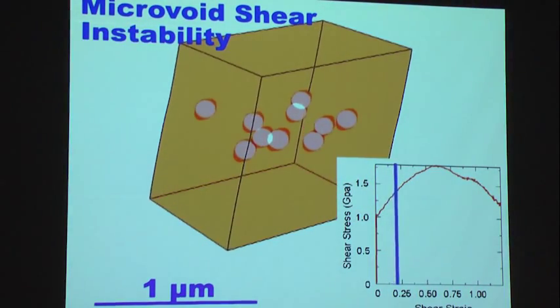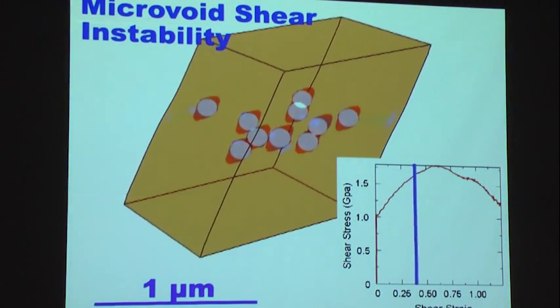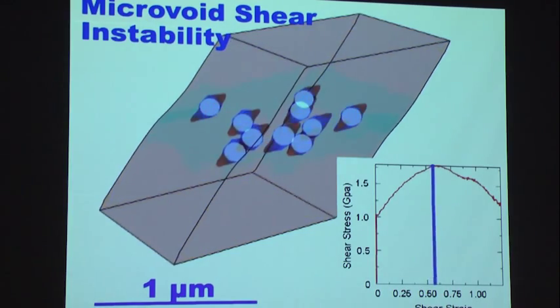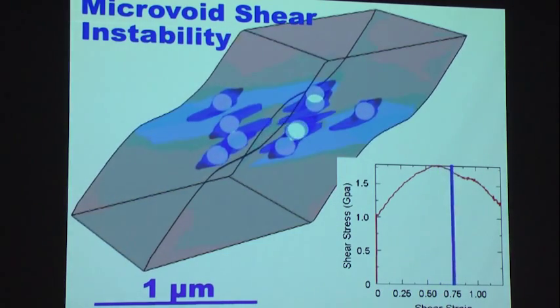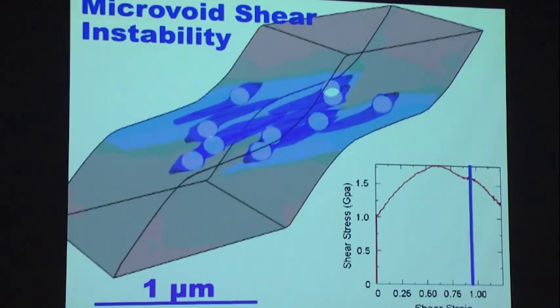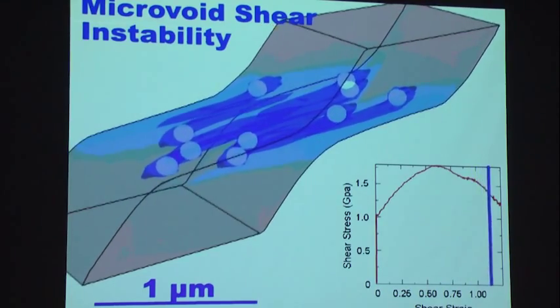Which we simulate here. So these particles are allowed to separate at interfaces. It gives us this stress strain curve where the microvoiding is driving softening, that in turn drives the shear localization and describes how the material goes all the way to shear fracture.